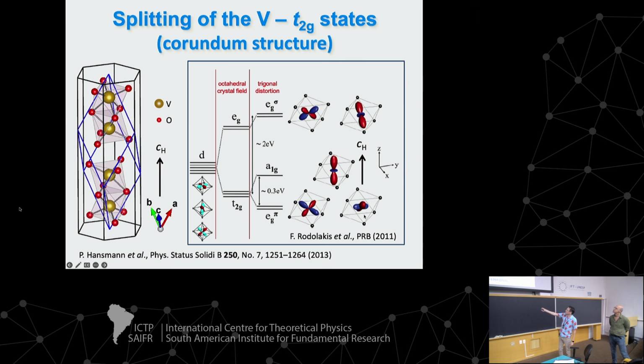In the crystal field of the paramagnetic state in V2O3, you should have 2 eg pi orbitals and 1 a1g orbital. So if we believe this, then in principle one of the Mott Hubbard band that is all the time there at -1 eV is one of these two. The other quasi-localized state is the other orbital, and the dispersive band is this guy. So it's just due to the crystal field splitting of the orbitals, if we believe that picture.